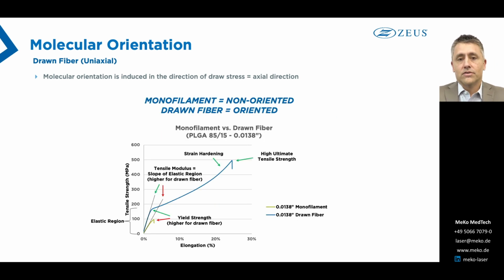So as a result of this uniaxial orientation, we get a stress-strain curve that looks a lot like this. So it's pretty easy to see why a braided stent would benefit from a uniaxially oriented fiber. Because if you take a look at that blue curve, that's the oriented curve, and it's got a much higher yield strength, it's got the strain hardening behavior, and a much higher ultimate tensile strength. If you contrast that with the red curve there, which is the non-oriented fiber, you see just really subpar properties.